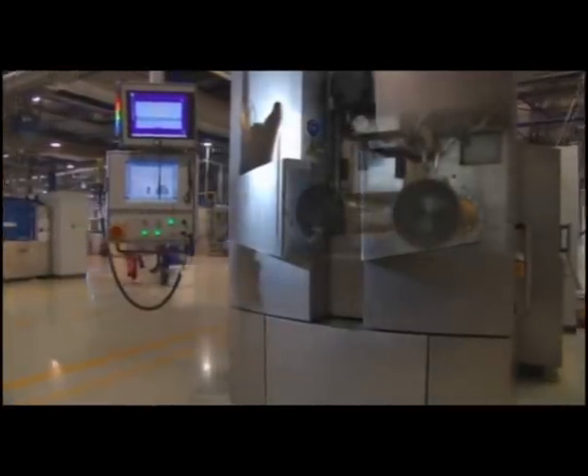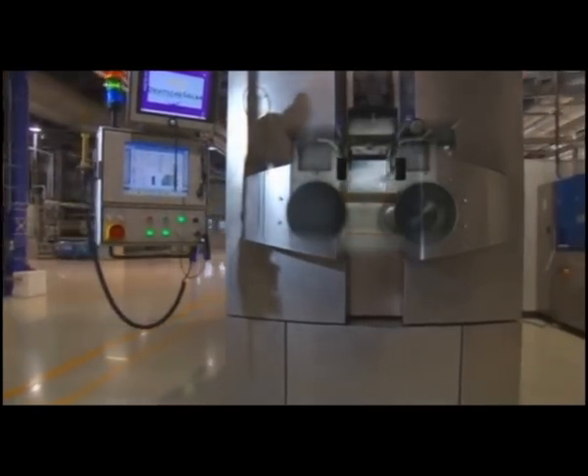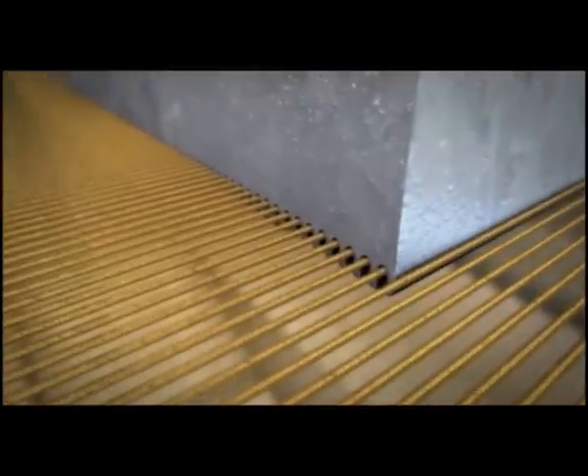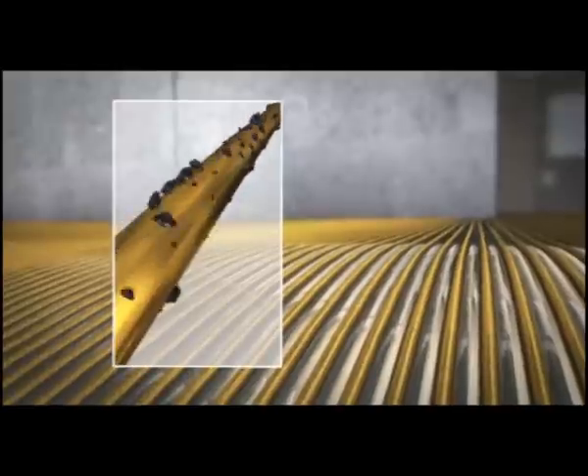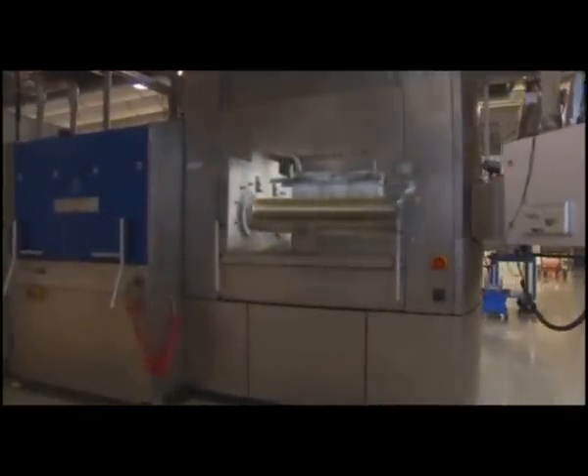The high-tech saw is equipped with two large track rollers. In contrast to the briqueter, a special wire of roughly 700 kilometers length runs across it at high speed, creating a rotating wire field through which the silicon bricks are pushed. The wire transports slurry. Its fine particles slice the silicon brick into wafers that are approximately just 0.2 of a millimeter thick.